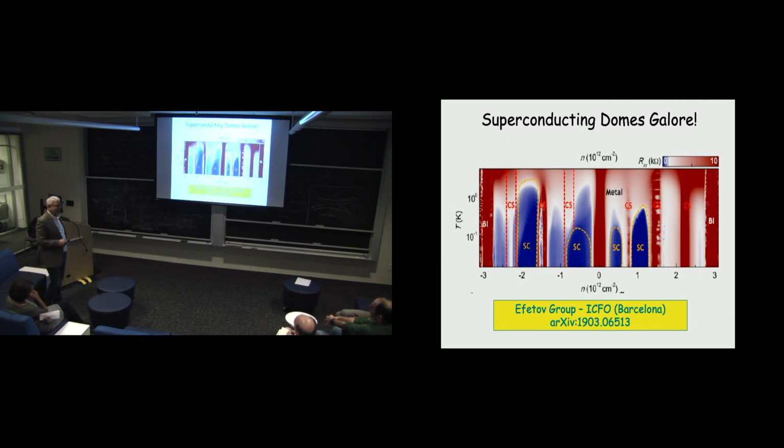Another quick question: do the insulating states occur at half filling of the Moiré lattice? So they occur at 1/8, 2/8, 3/8, 4/8, 5/8, 6/8, 7/8 of the filling of the flat bands. And it's eighths rather than halves in the case we're used to, because the usual case is electrons only have a spin degree of freedom. Here we have spin and valley, and there are 2 flat bands, conduction and valence. So that's the difference. And there are lots of superconducting domes.